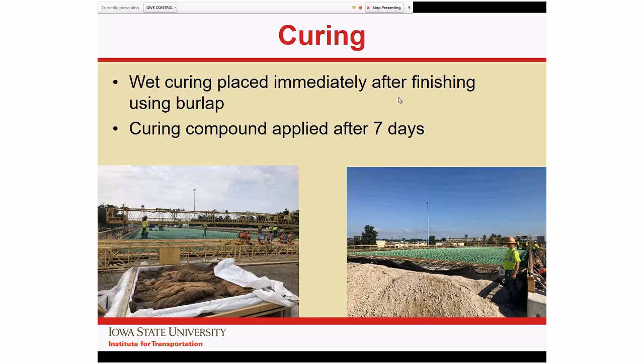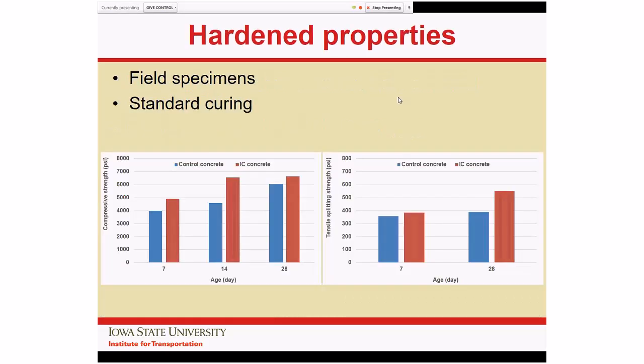The curing was based on the higher specification, wet curing placed immediately after finishing using burlap. That was stripped off after 7 days, and a curing compound was applied. And that's not a bad way to go.